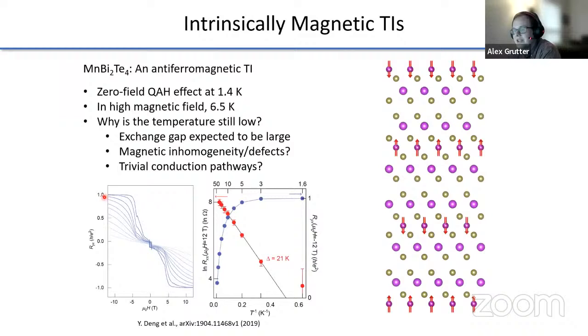And so if you do this, you can in fact achieve the quantum anomalous Hall effect as demonstrated by Deng et al. They found a zero field quantum anomalous Hall effect at 1.4 Kelvin and, in a high magnetic field, up to 6.5 Kelvin. So this is a huge improvement, but it's still lower than you might expect from theoretical calculations of how big the exchange gap is.